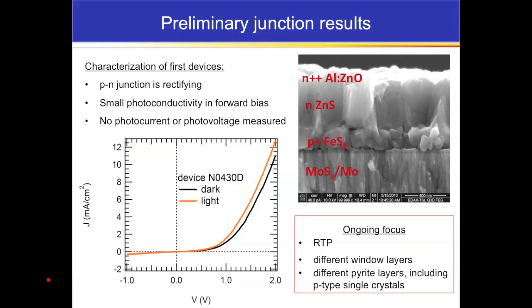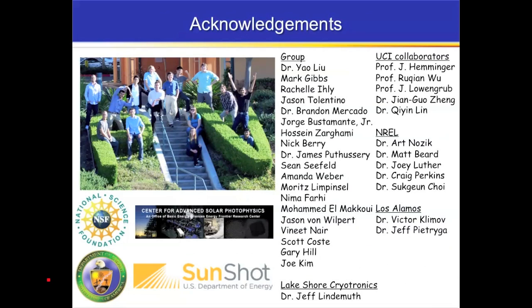And we've started to do this now. We take pyrite layers on moly. We deposit, for example, zinc sulfide and then a top metal contact. And we get decent rectification, but so far very, very little photo response. We've just started doing the controlled annealing, and so this is not after any annealing. This is just as made. So what we're trying to do in the future is to use rapid thermal processing, explore lots of different window layers, and also different kinds of pyrite materials, whether they're single crystalline or polycrystalline, and to try to get us out of this kind of potential well that pyrite has been stuck in that we think is from the surface.